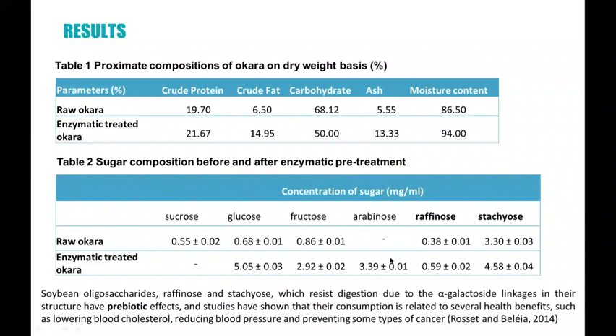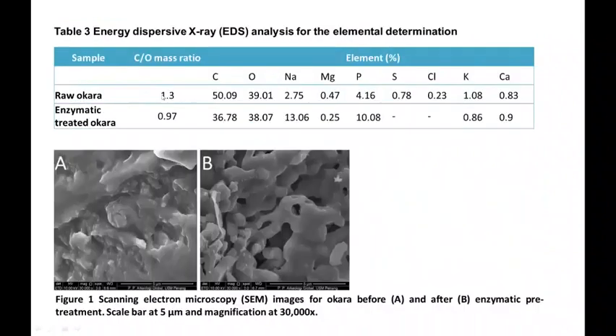In this enzymatic treatment, it increased the raffinose and stachyose. These are soybean oligosaccharides, which resist digestion due to the alpha-galactoside linkage in their structure, and have a prebiotic effect. We also sent for the energy dispersive X-ray, the EDS analysis, for the elemental determination. We can see the C/O mass ratio is decreased because the carbon reduced during the hydrolysis. We also sent for the SEM analysis. We can see the structure of the okara is broken. It has some holes here and it releases all these sugars and proteins from the cell wall.